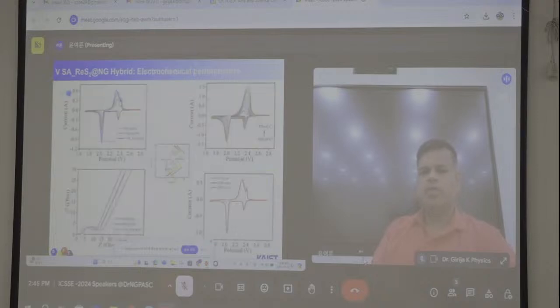When we go for the vanadium single atoms compared to the metal nanoparticles, like metal nanosulfides, like vanadium rhenium sulfides, I am going to prove the single atom behavior. For the vanadium single atom, the blue one, you can see the anodic current density is higher and the cathodic is also very high. Anodic density is usually for charging and cathodic is for discharging. When the cathodic is higher, the discharging will be high. Usually in many batteries the charging is very high and not symmetric, with very fast discharging. But in our case, it is almost symmetric.